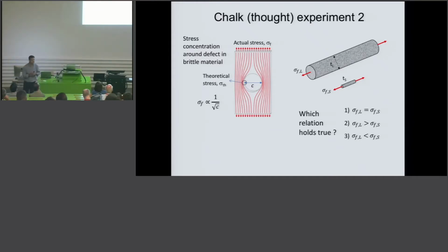What do you think? Who votes for 1? For 2? For 3? Yes! So why is that? The strength of the large one will be smaller because the size of the defect, the critical defect, scales with the size of your platelet. So we can do an approximation and say the size of your defect should be proportional to the size of your platelet or your rod. So this allows us to use this very simple relation also to predict the dependence of the strength of our platelet on its thickness, which is quite interesting. It means that the thinner you would make these platelets, the stronger they are.